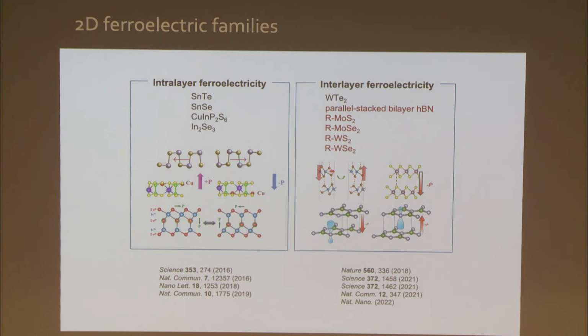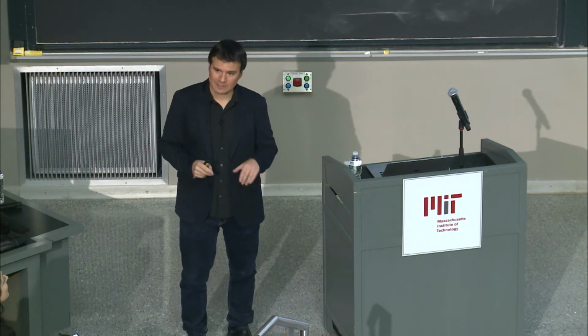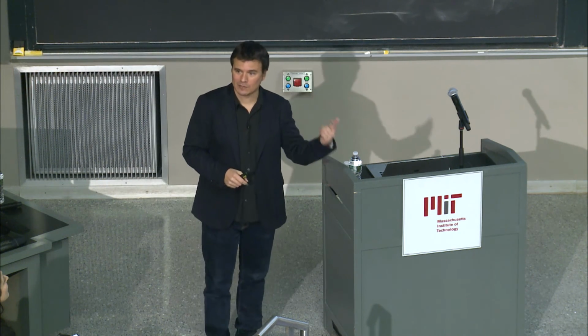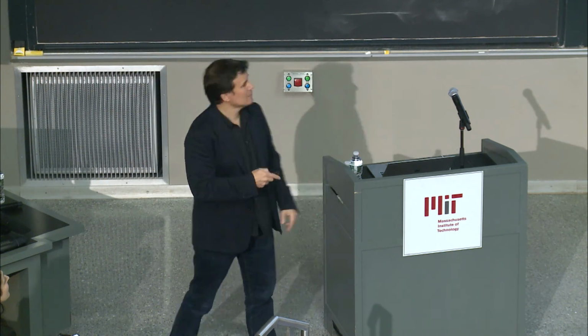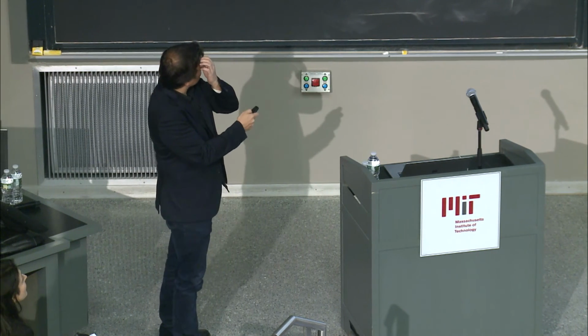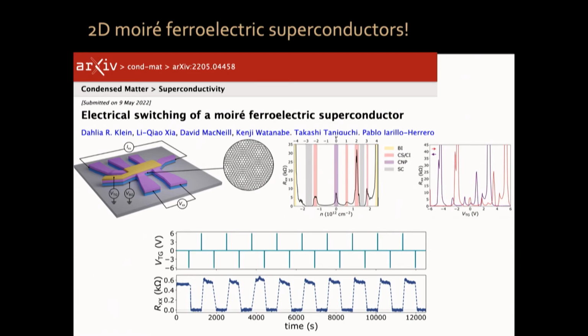Moreover, this ferroelectricity can be engineered in systems that have any order, systems that are also ferromagnetic, or superconductor, or you name it. For example, recently we just posted electrical switching of a moire ferroelectric superconductor, where we can switch due to ferroelectricity between a superconducting state and a resistive state. Okay? Zero resistance, finite resistance, and we can do this at will as many times as we want. Okay? This was by using magic angle graphene.